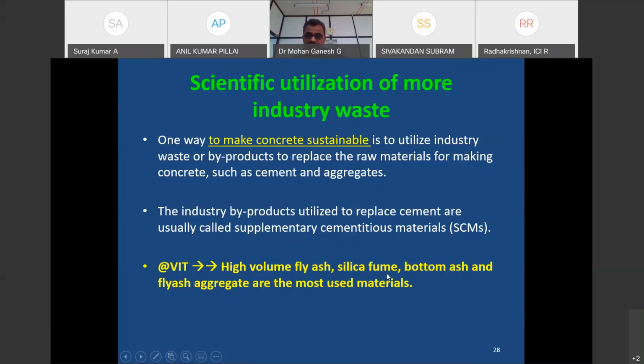Silica fume also we have used up to 10%. Bottom ash up to 50% we have used in place of sand. Again, fly ash aggregate also we have done with coarse aggregate. So these are the most common materials people are using nowadays.